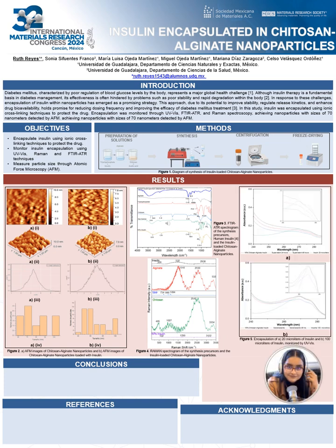Regarding UV-Vis, this technique helps us determine the wavelength at which insulin appears, and we have this characteristic shape with peaks observed at 265 to 270 nanometers. We measured insulin diluted in the total amount of solvent used to form the nanoparticles, then measured the absorbance to see how much was encapsulated during synthesis. And finally, at 24 and 48 hours, we found that if we let the system sit, more insulin is encapsulated, as observed by a decrease in absorbance.